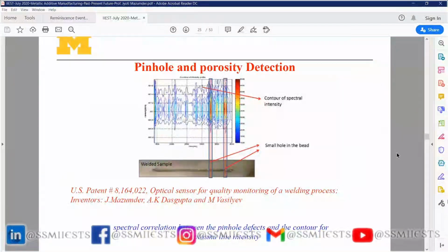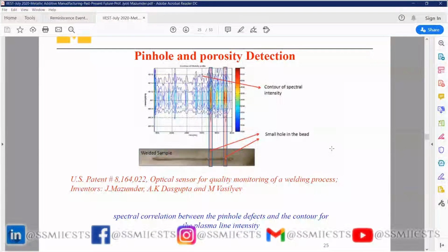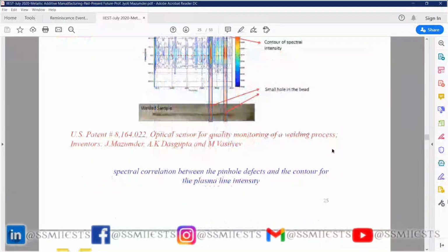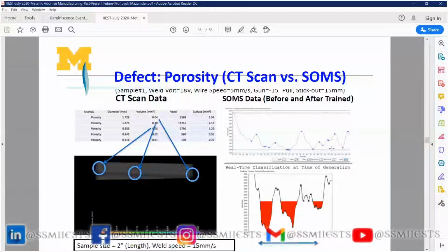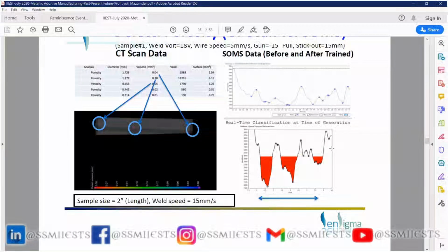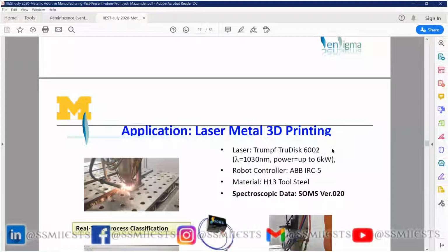So what we do, when you look at the plasma, by looking at the nature of the emission, we can find out whether there is a defect or not, especially porosity. There are small holes created if the deposition is not correctly done. And we have patented that. This technology is becoming very attractive to industry because they can find out the defect online instead of waiting for weeks of TEM and SEM and all those kinds of things. So that's creating a lot of interest.